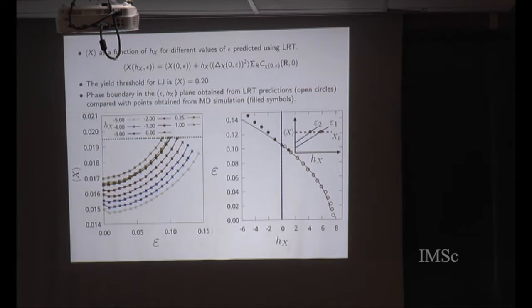We know that for the harmonic solid, we don't know it for Lennard-Jones. For this particular density and temperature, we found out that it is around 0.2. We suspect, and these are calculations which a student is doing right now, that this can be scaled, and that finally there will be only one scaled parameter for any particular system. Okay, so this is the maximum non-affineness that a crystal can take. Once you have that, then you can calculate a phase diagram, a dynamical phase diagram, and this is this line.